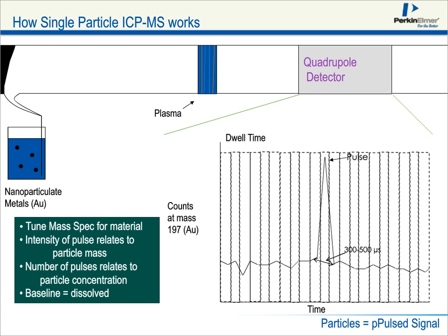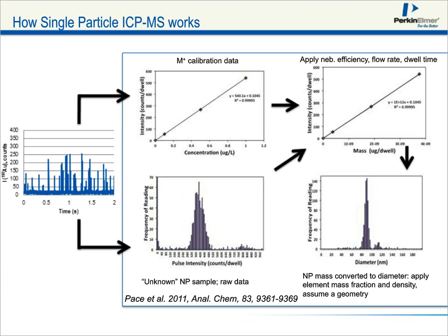Now, from a mass perspective, when you are using single particle ICP-MS, you do not need particle standards for the particle that you are measuring. All you have to do is basically use the same ionic standards that you use on a day-to-day basis in your ICP-MS. You're going to be calibrating the instrument using those solutions, and you're now going to calculate something called the mass flux. We're actually calculating the response of an instrument based on time for the amount of ions that it's going to receive. And this is what then allows us to convert a particle signal acquired over a certain amount of time, quantitate the ions in it, and correlate that to an amount of mass.